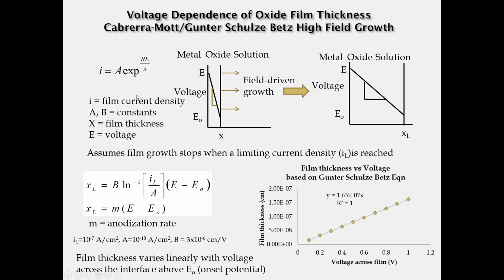So you could take this equation and put in limiting current and limiting thickness where that film will essentially stop growing, rearrange that, and note that the terms out in front of the voltage terms are essentially constants. If I lump them together as M, you can see that the thickness of the oxide depends on this constant M and how far the voltage is away from some onset potential, the passivating potential. And so we would expect from this that the thickness of an oxide film will vary linearly with the voltage applied across that surface.